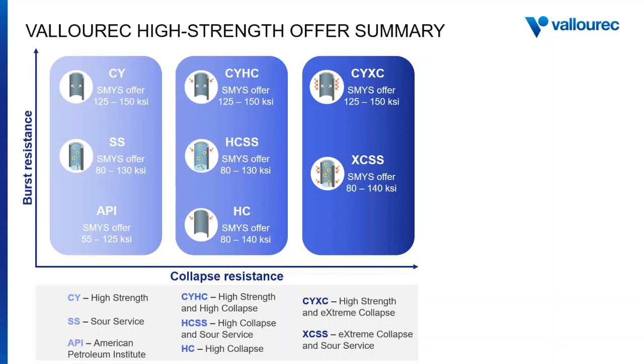On the horizontal axis, we can see that the collapse resistance of a tubular can be increased by moving to high collapse grades that offer an enhanced external pressure resistance thanks to a more restrictive manufacturing process than used for API grades. When an even higher collapse resistance is needed, then we can move to extreme collapse grades that can be achieved by either restricting the manufacturing rules even more than for standard high collapse grades, or by the dual performance basket methodology that identifies and segregates the most performing pipes of the lot.